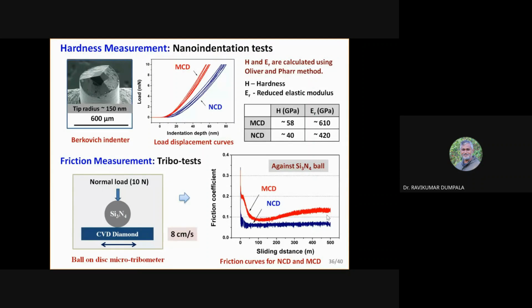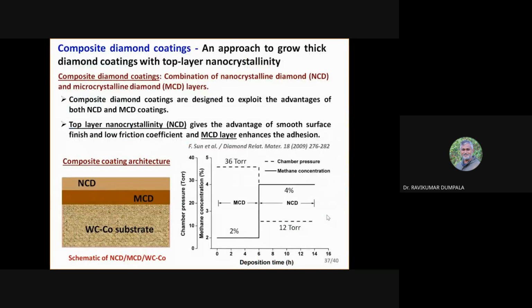That is why we go for duplex coatings or composite coatings, whatever we call them. It is the same material but with different microstructures having different properties, so you use the best of their properties. First you coat the MCD on the cutting tool, so it sticks better to the surface. On top you coat the nanocrystalline diamond, so it has a better friction coefficient. You use both properties and get a better, high performing material. So definitely people will adopt this process. This is a technology which we developed. We have even filed a patent, and one industry, Kapindra in Chennai, has adopted this technology to develop the coatings. Performance increased almost 3 to 4 times compared to independent layers.